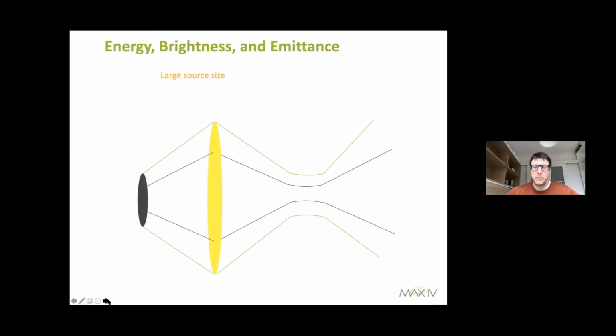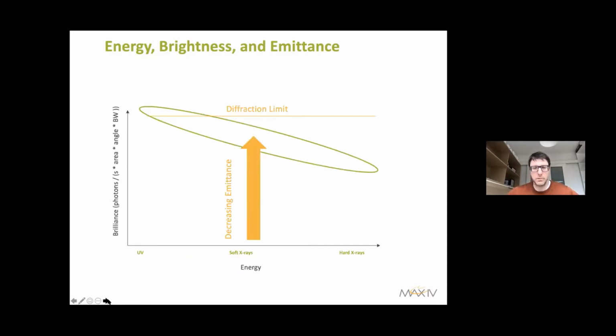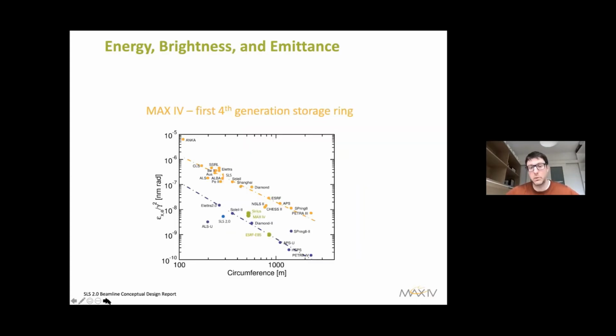There are ways of bypassing it, for example using a secondary aperture, but that cuts our flux and thus decreases the brilliance. So what we want to do is decrease the influence of the source size, and the source size and source divergence are called emittance. We need to lower it to reach this diffraction limit, and that's exactly what MAX IV does, or did differently from other synchrotrons. At least it was the pioneer of this fourth generation storage ring technology that brings the diffraction limit to high energies.